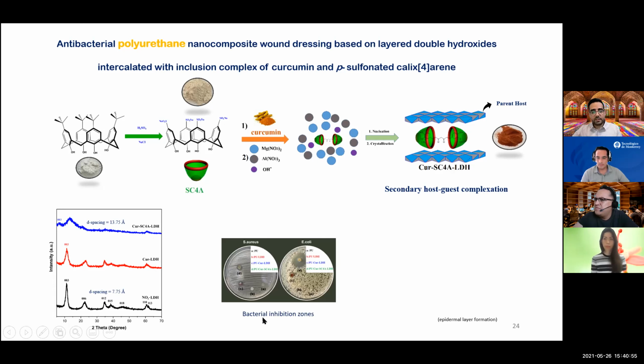And the other thing is the test regarding the bacterial inhibition zone, because as I mentioned, we want to use the curcumin as an antibacterial agent, and you can see here that I already put different codes for different materials. PU is the pure polyurethane, PU-LDH is adding nanoparticles or nanosheets of the LDH without any modification. After that is the LDH and curcumin without using the primary host, and the last one is the secondary host-guest complexation. And you can see the inhibition zone for both bacteria, the gram negative and positive. So you have better results regarding these samples that I mentioned. We have a really nice, high concentration and high bioavailability of the curcumin in this regard.